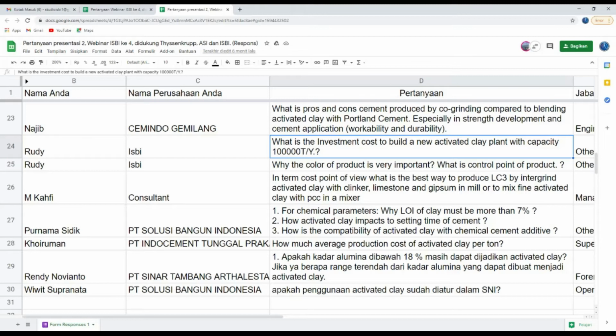Let's say standard, if you talk about 1,000 tons per day, or maybe 900 or 800, this would be in the range of EPC, something between 20 to 30 million, just to give you a rough estimate. But this also depends on the clay properties, on the fuel you are using, and on the reducing or oxidizing process. So again, just very rough. We need to know what clay we are talking about and what the moisture is to give a precise cost estimate here.